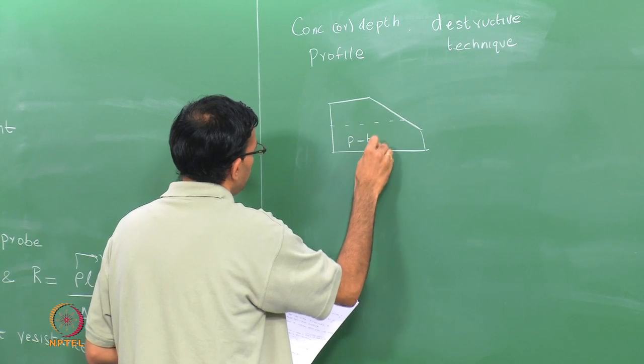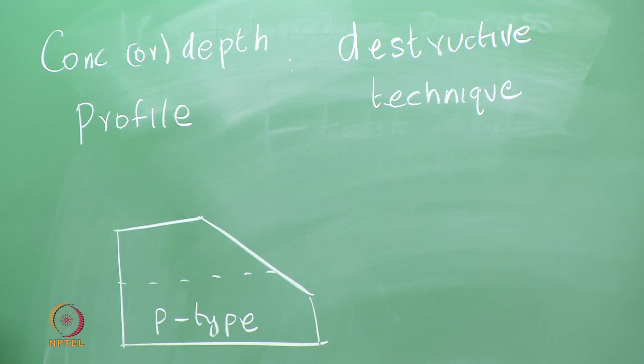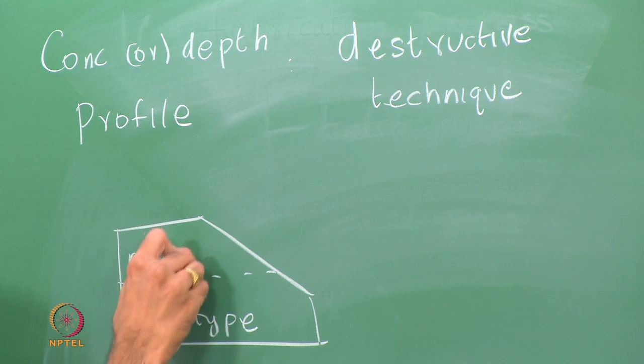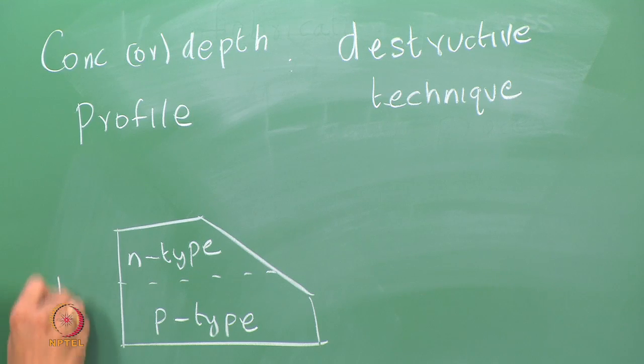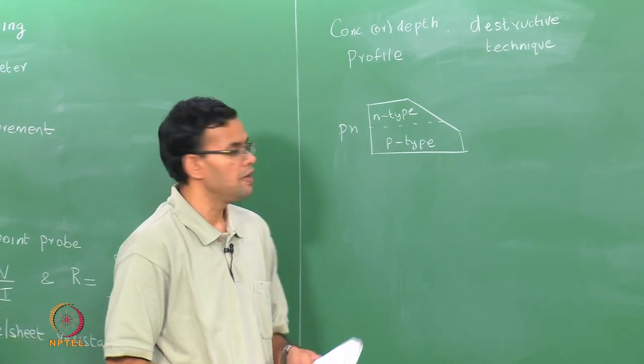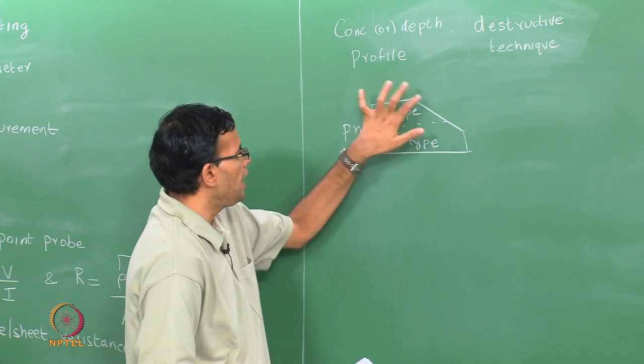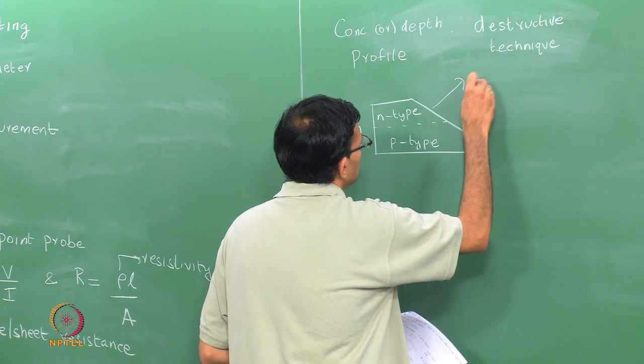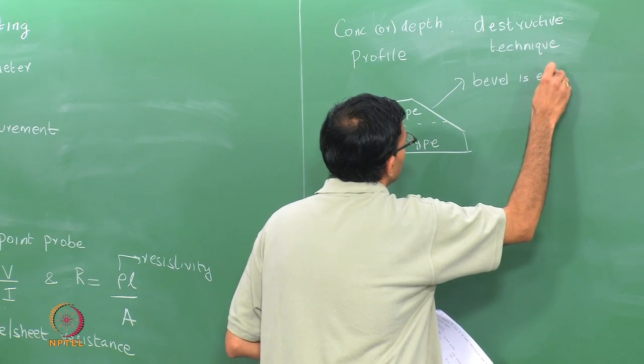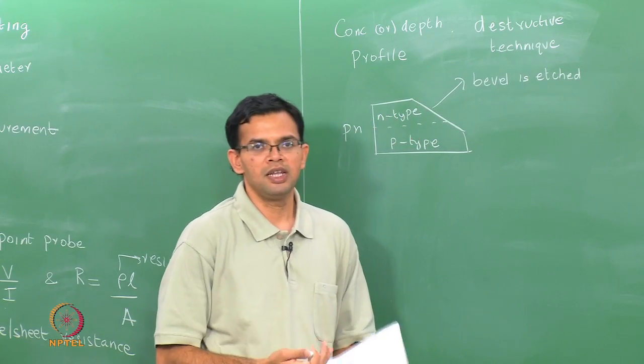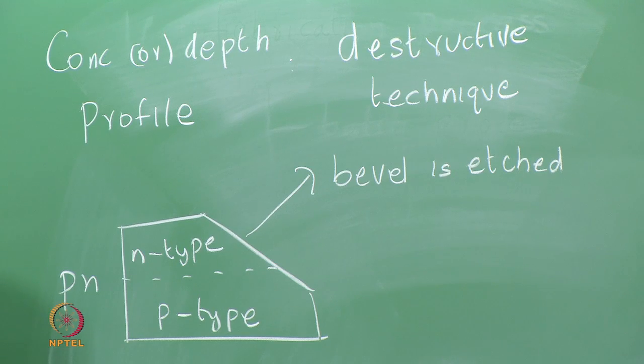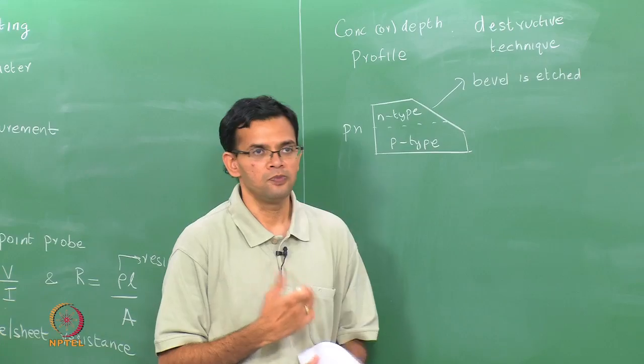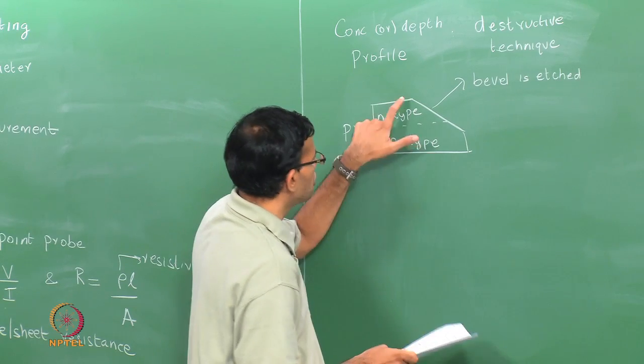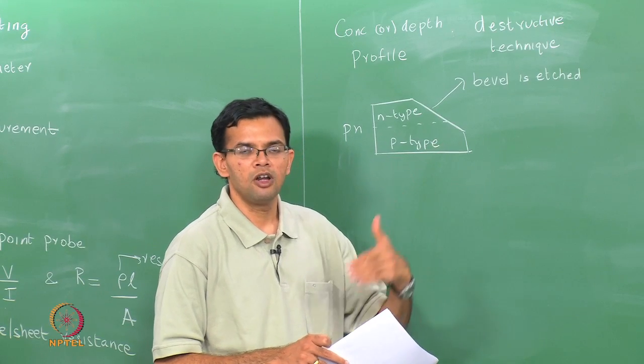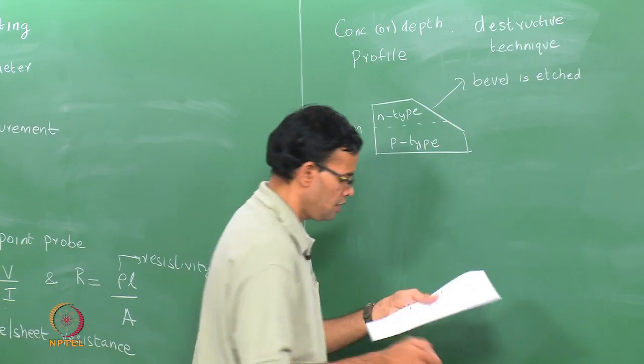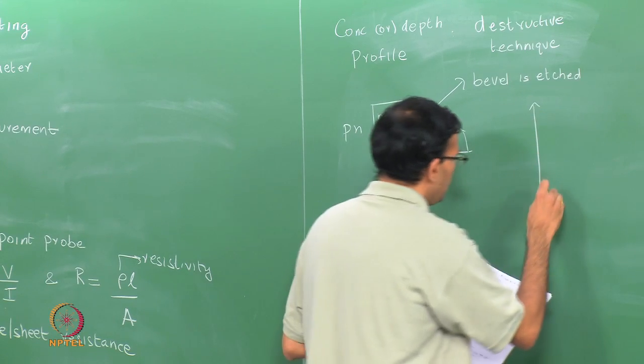So, we start off with a p-type material. We have doped a certain region of this material n-type up to a certain depth, so that we now have your p-n junction. We can find the depth of this p-n junction by etching a bevel onto your wafer. This is again usually done by using lithography in order to expose a certain portion of the wafer, which is then etched through, and then measuring the resistance as a function of length along the bevel. As you move along the bevel length, you are also moving down in thickness. So, you can measure the resistance and relate that to the concentration.